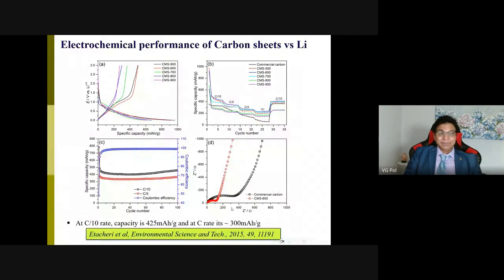We also study the impedance spectroscopy. Just wanted to make sure that impedance spectroscopy measures the resistance in the system. When you have a battery made from this packing peanut, one can think that this trash should not work well, or trash-derived material should not work well. In fact, this material works better than your traditional graphite that you can buy from the market, with minimum resistance in the system. And this originates from this thin sheet of carbon.